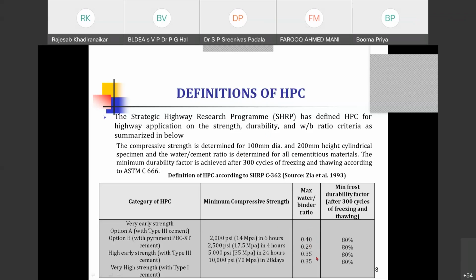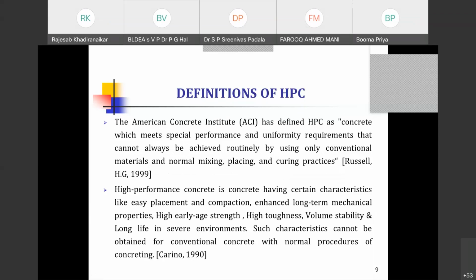And the water binder ratio varies anything between 0.35 to 0.4, and it depends. Even less than 0.25, 0.2 are also used. But the threshold limit is 0.35 nowadays. If you go beyond 0.35, you may get strength, but some of the performance characteristics are impaired. So that's why nobody goes beyond 0.35. So 0.3, less than 0.3 or 0.35, like that. And after 300 cycles of freezing and thawing, 80% is the threshold limit. It should give at least 80% performance, and then only it is accepted.